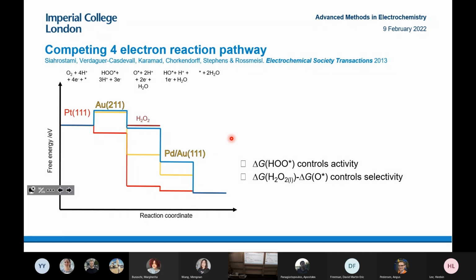If you look at the similar activity to gold, and actually look at the free energy diagram for palladium gold, what you find is that there's less downhill to make oxygen, but the binding energy to OOH is quite similar. So the binding energy of OOH controls activity, but the selectivity, which would be the difference between oxygen and hydrogen peroxide, is much lower. So this could explain why it's more selective.